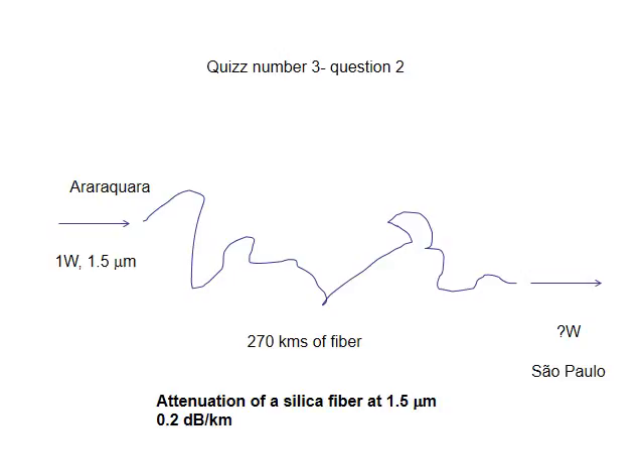To calculate this value, you will just take into account the intrinsic absorption for silica, which is 0.2 dB per kilometer. Of course, in the real world, the attenuation is composed of different terms such as scattering loss, bending loss, radiation loss, leaking modes. We'll come back to this talking about optical fibers.